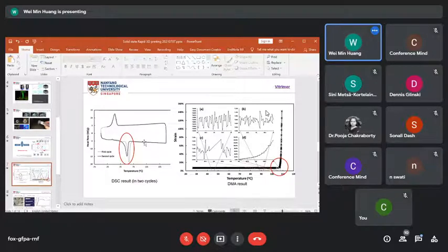But before that, at temperatures below 100 degrees, the material is able to maintain its shape, just like a semi-crystalline material. But the difference is that the cross-linking is reversible, which means that if you heat up to even higher temperature, eventually the cross-linking is going to be fully removed. Okay, so this is a unique feature of Vitrimer.